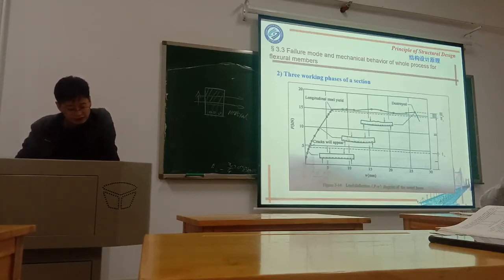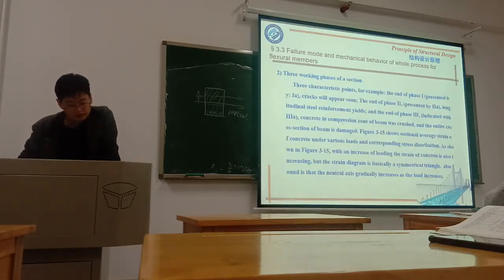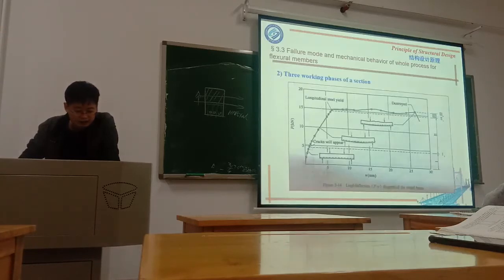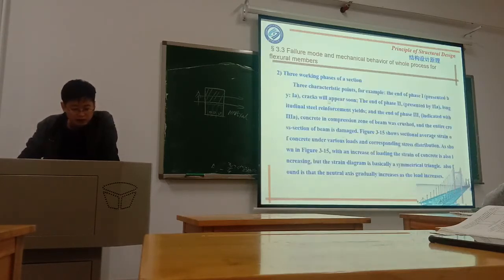You see in the second phase, the crack appears, and in the third phase, the crack develops and the concrete has cracked through. So there are three characteristic points. For example, the end of phase 1 is presented here. Crack will appear soon. At the end of phase 2, the longitudinal steel is still approximately at yield, and at the end of phase 3, the concrete in compression is crushed, and the entire cross section of the beam is damaged.